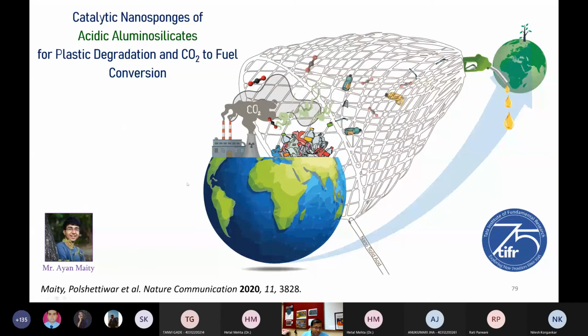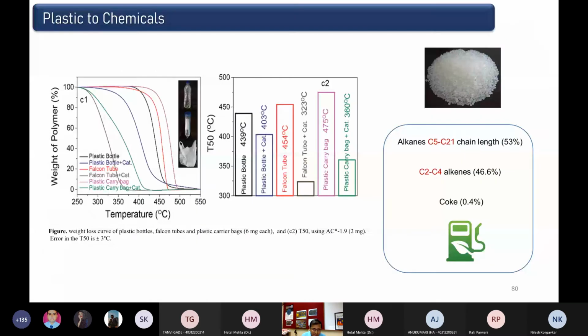And that's where one of my students came up with this acidic material, acidic aluminosilicate, where you replace some of the Si from the SiO2 network with aluminium, and you get a aluminosilicate, which has a strong acidity and porosity, and which allowed us to then degrade the plastic at a lower temperature, say around 100 degrees Celsius lower.